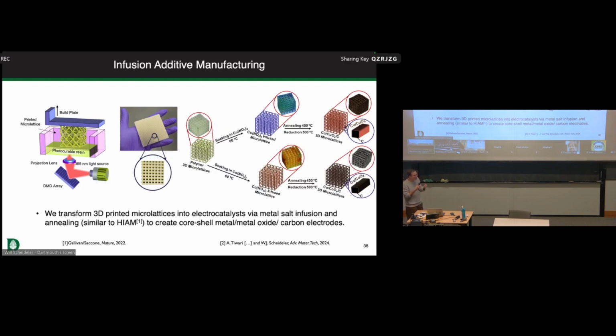to create a 3D printed metal. In this case, we're forming a core shell structure that has some active material. This is actually ideally what we want for the catalyst, right? Any material that we introduce, we want it to be in contact with the electrolyte, because that's where it's actually doing the chemistry we want to happen. In the core of the lattice instead, at each beam element, we have that graphitic carbon that we developed earlier.